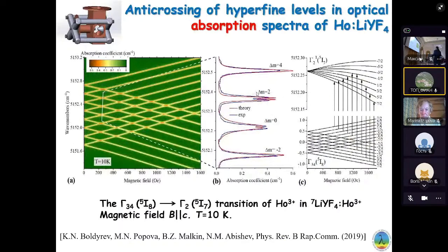Three years ago, we built our magnetic system and investigated the spectra of these crystals in absorption. So there is a magnetic field, there are wave numbers, and there is a color map of the observed hyperfine levels. And for the first time, we directly observed the anti-crossing in the optical region. So there it is at 2 micron, but we observe such a picture in the visible region too. And this work was published in 2019.